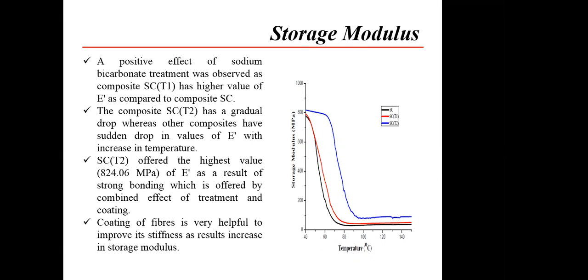In this graph there are three regions. This one is the glassy state, this one is the transition state. There is a huge loss in stiffness. As we increase the temperature, the value of storage modulus declines, because if you increase the temperature, the storage modulus capacity of the composite reduces. The mid one is the transition region, and the last one is the rubbery region. Storage modulus dictates the stiffness of the material, how stiff the material is.